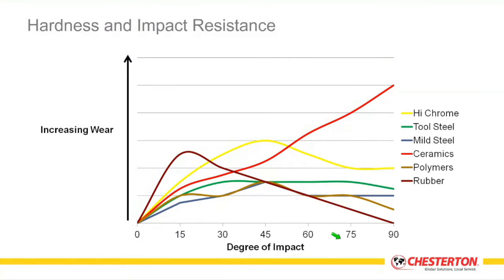And when you're looking at degree of impact here, the degree of impact is critical, because when you're dealing with rubber-based materials, you're going to get relatively high wear at your low angles of impact, and as you move towards higher and higher impact angles, the rubber systems actually have lower wear rates. Conversely, if you look at a ceramic-based material, as you move to higher and higher impact forces, the wear rate increases dramatically. That's due to the brittle fracture nature of these materials.